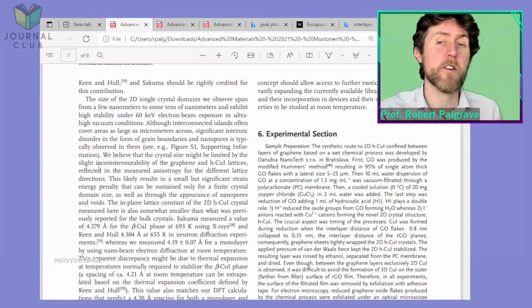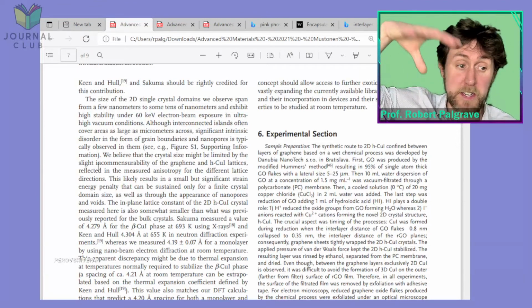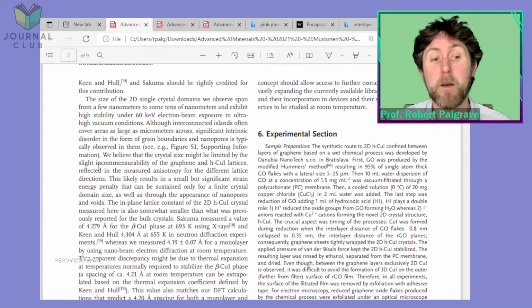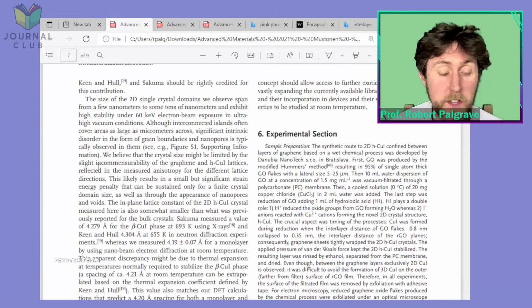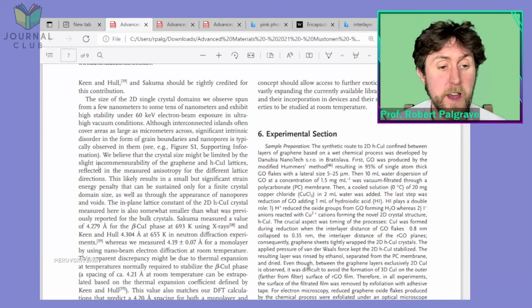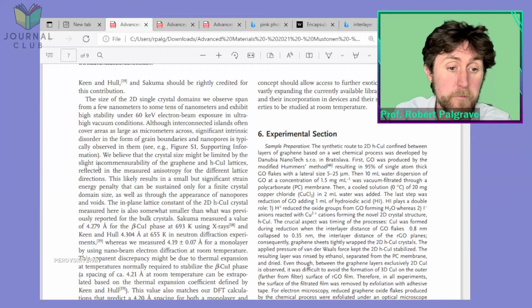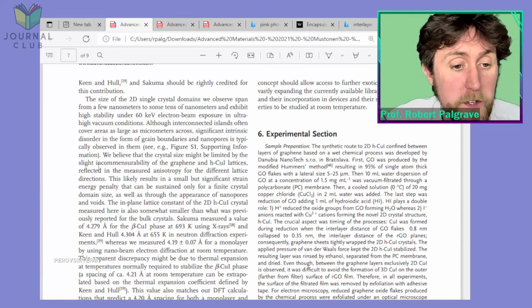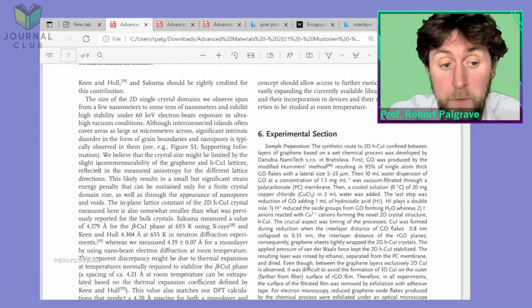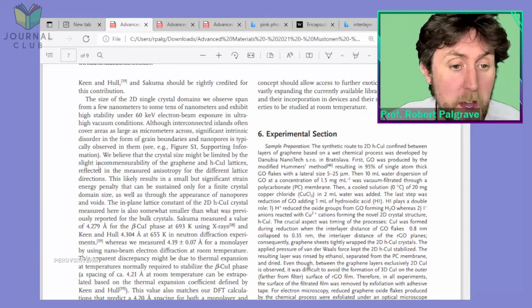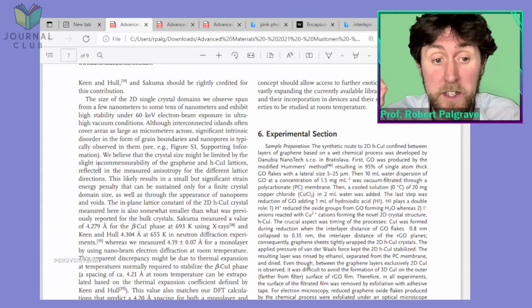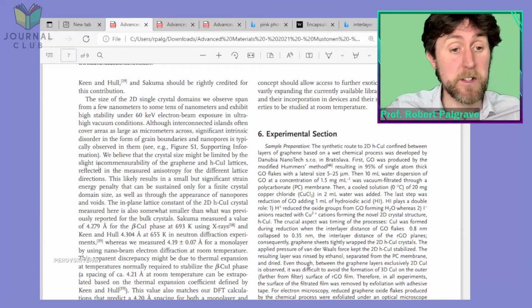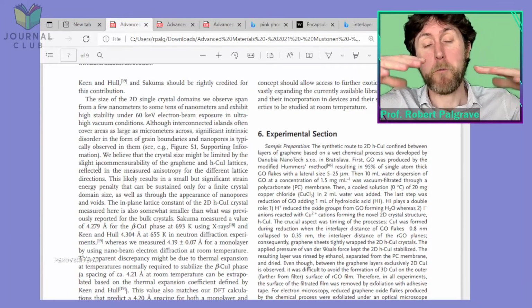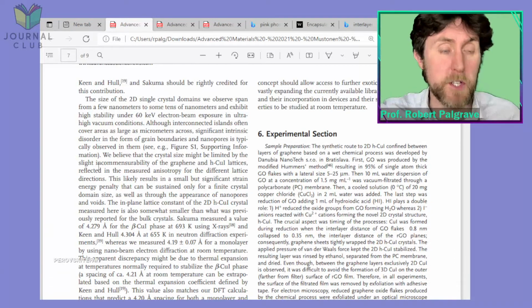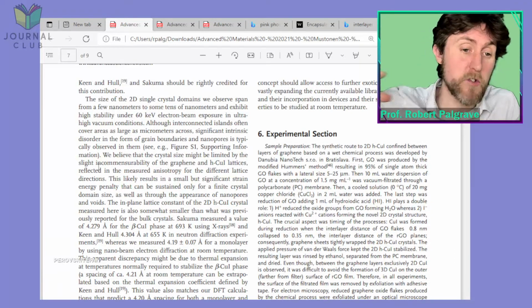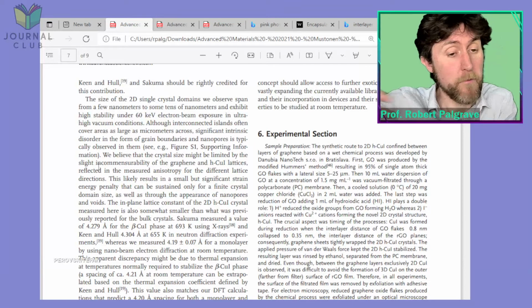Okay, so I mentioned earlier how I thought the fact that those lattices match up very well is perhaps a good reason why you're able to encapsulate cuprous iodide inside graphene. But they're saying there's a slight incommensurability, a slight difference in size of the lattices, so that might limit the size of the domains you can actually make, because the bigger the domains you make, the more strain energy you put into stretching one or both of the lattices to match up with the other one.